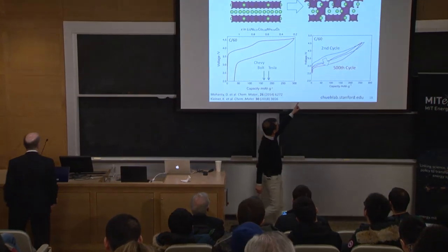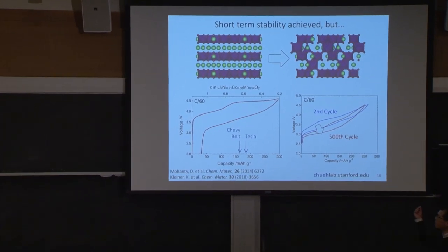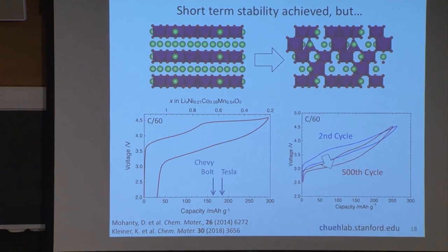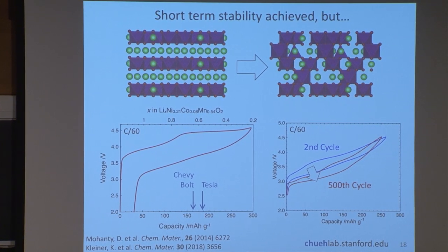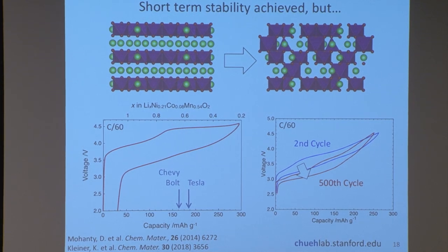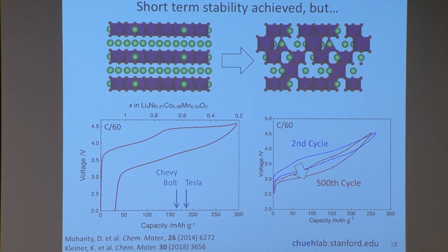Yeah, so the capacity fade is actually really small. If you look at between the second and the 500th cycle, it's only about 5%, which is actually pretty remarkable. Okay, that probably comes from some small loss of lithium or transition metal in the system, right? So you're losing the lithium or transition metal inventory. That's possible. But we're pretty encouraged by the fact that the capacity is not decreasing overall. So overall, it's still utilizable. Is that the voltage is getting lower and lower, and that impacts your energy density of the system. Yeah. Or the oxygen is slowly leaving the material, say over thousands of hours, and that's entirely possible as well.